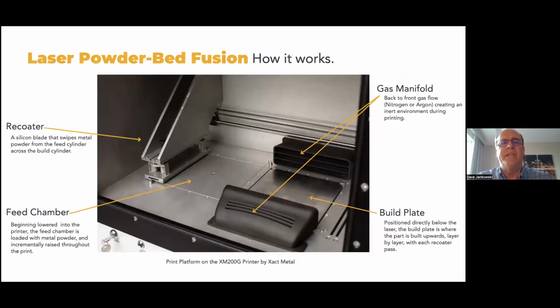The technology I'm going to focus on is called metal powder bed fusion or laser powder bed fusion. The technology essentially consists of using a high energy laser to melt a thin layer of metal powder, and then to do that sequentially over and over again. What you're looking at now is the interior of what we call the build chamber of a laser powder bed fusion printer. On the left side, you see an item called the feed chamber. That is essentially lowered and filled up with metal powder. Metal powder, steel powders, inconels, aluminums, titanium, copper, cobalt, chrome, and so forth. Essentially, any metal which you can weld, you can print, because this is essentially a micro welding process.